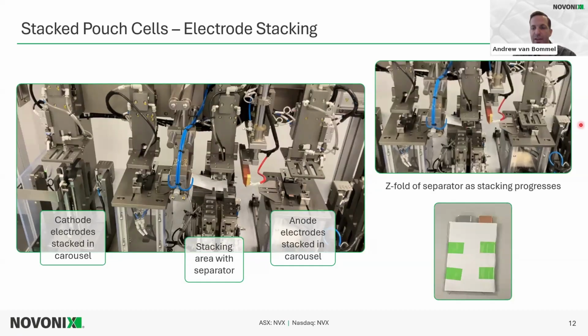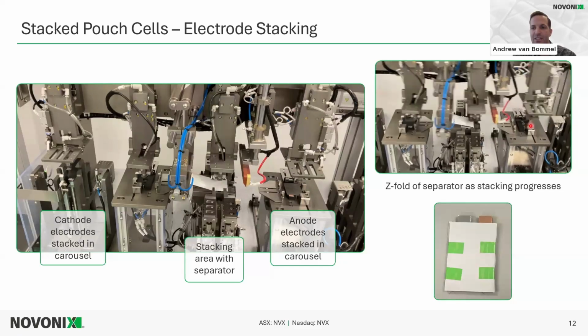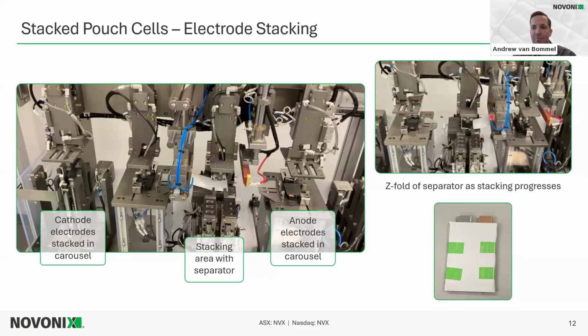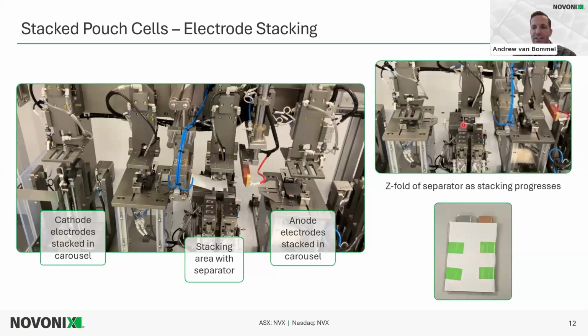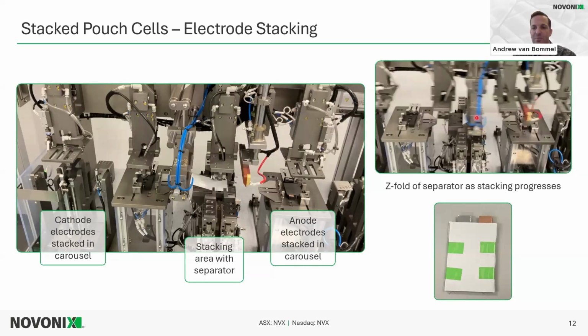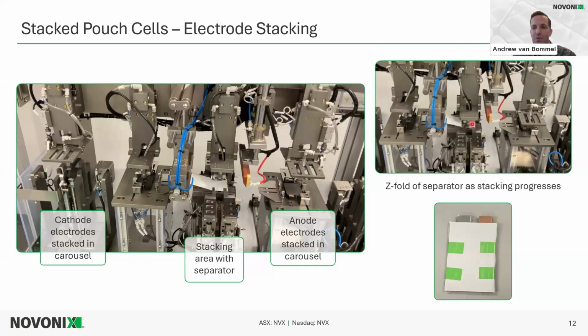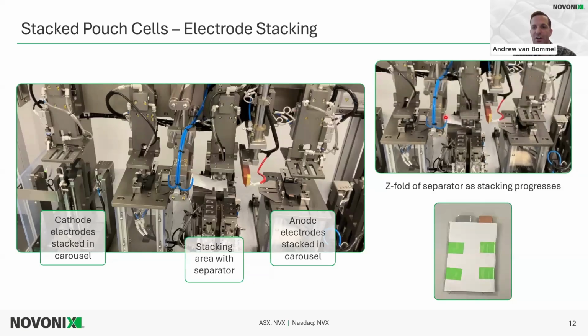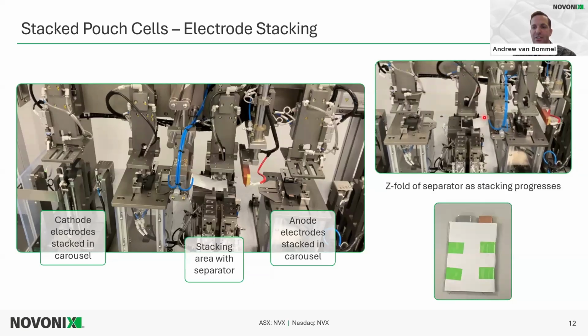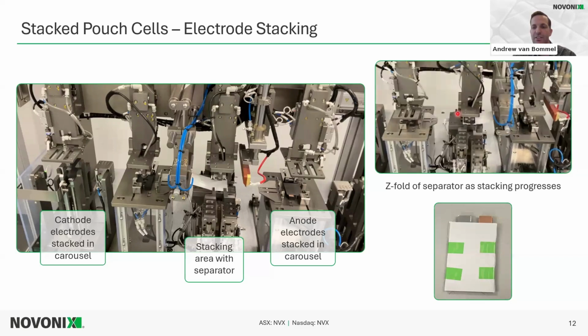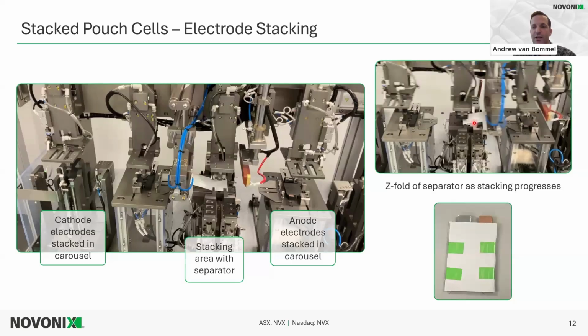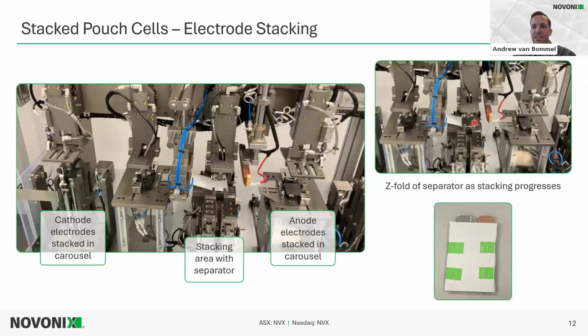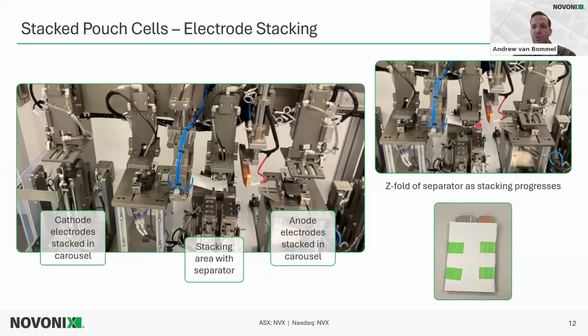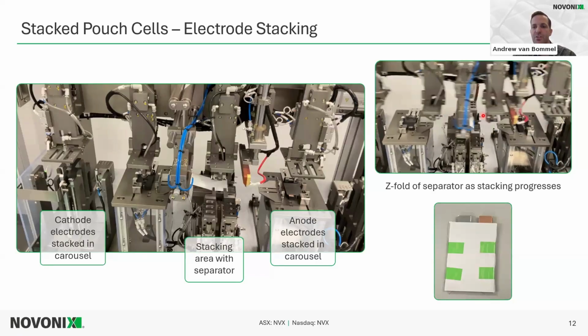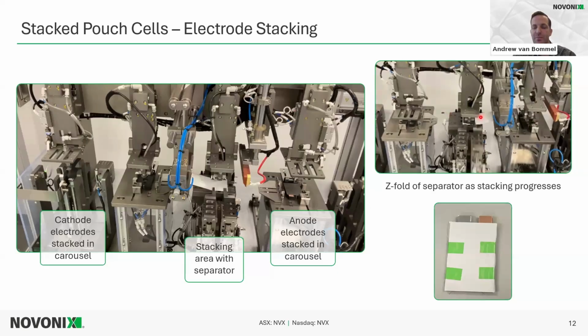anode. So it's from the carousel out of the frame here, and it brings it to this area. And then that anode is grabbed and placed on the stack. And then the separator moves, and then it does the same to the cathode. And as that happens, the separator moves over the anode and then over the cathode, and that continues. So the stacker can be programmed depending on what capacity is required, and that will also change what the stack height is as well, which we'll discuss later. So that continues until the program is done and the capacity desired is reached. So here's the final cell shown once again.